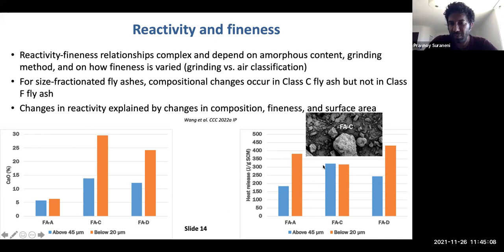So what's happening? Well, this is a very strange fly ash. It's an unconventional fly ash, which has a lot of surface porosity. So the fineness in this case is not controlling the reactivity, or at least not the fineness measured from laser diffraction, because the specific surface area does not have the same relationship to particle size that other materials have. Because of all the pores on the surface, the coarse fraction and the fine fraction actually show very, very similar reactivity. There are also changes in the phase content in the coarse and the fine fraction.